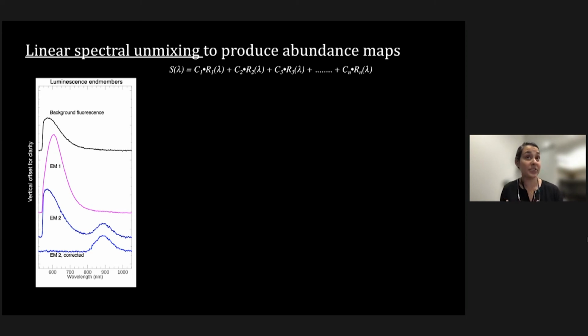So the end members that I found, or the spectral signatures that dominated the luminescence cube, are stray light, which makes sense. It's hard to get rid of. But then we also have Madder Lake, which I expected because I saw the reflectance profile. And then there was a signature that had background, but it also had a near infrared luminescence bump. And this to me indicated the presence of Egyptian blue. Now, in order to do some creative mapping, I actually corrected this by removing that background peak. And then because all of these signatures together are contributing to the luminescence signal, I performed linear spectral unmixing to produce abundance maps to see how each of them are contributing.